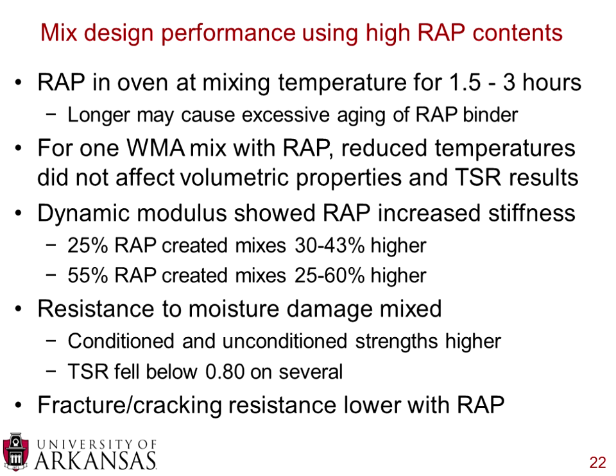Something they found out about this, though, is by using RAP, they increased both the conditioned and the unconditioned strengths. But in the process of raising both the conditioned and the unconditioned strength, they actually decreased the ratio. So the TSR fell below 0.8, but they were actually getting higher strengths. So that's something that's always a little complicated using the TSR in a specification, is that you can actually get better performance, but the ratio decreases.